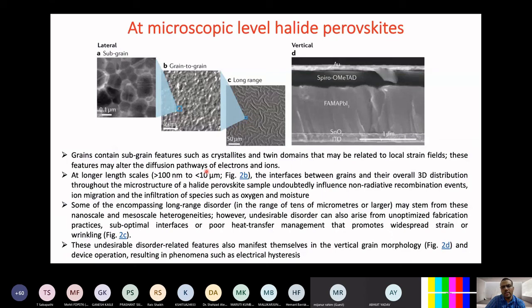I will be able to share these slides with you, so you will be able to see. And this is all there in this perovskite semiconductor device structure, with transparent conducting ITO, electron transporting layer tin oxide, then the double cation FA and MA mixed lead iodide, and then the hole transporting layer is Spiro-OMeTAD and the gold contact.